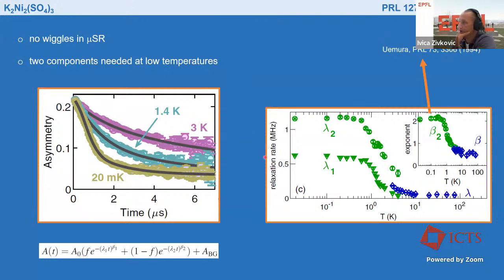But the way that we did it shows that the relaxation rates of these two components show the typical behavior of a quantum spin liquid, with a plateau occurring at low temperature. But what is more important is that one component, which is described with this beta 2 at low temperature, hits this value of 2 for the exponent, which, following this article, has been indicated as proof of the existence of a sea of singlets, which here and there release an unpaired electron, which then generates the dynamics of this type.